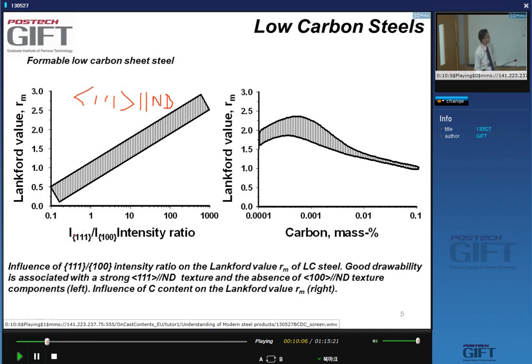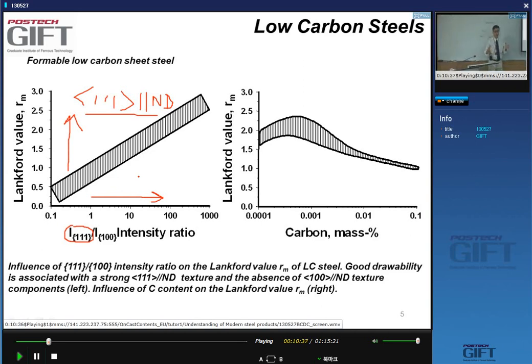And you can see here, this is the intensity of the 111 reflection peak in X-ray diffraction. If I have a lot of grains that have this orientation, then this ratio of the intensity of the 111 reflection over the 100 reflection will be high. And as a result, I will have a high R value. So this tells you that the R value is related to texture, and in particular, the 111 fiber texture, gamma fiber texture also called.